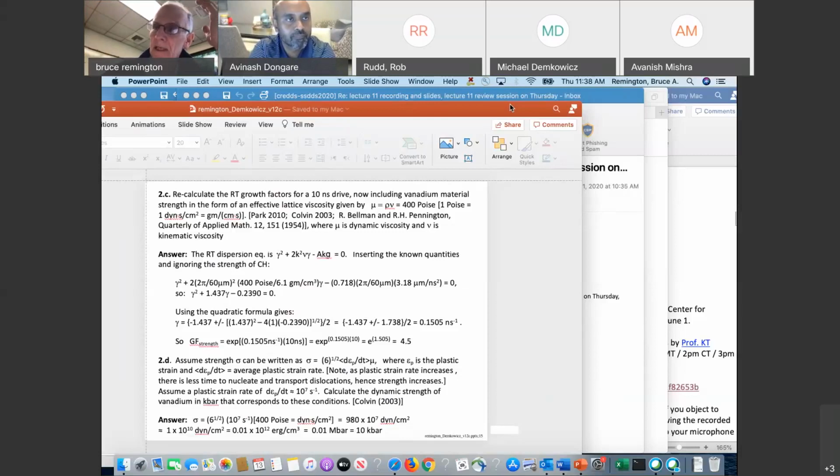One team, the strength team that I'm on, has usually been trying to keep the temperature low, because in the beginning days when we were trying to develop the experiments, there was always the worry that we unintentionally melt the sample. So we got used to running experiments where the predicted and measured temperatures were factors of 5 to 10 below melt. But more recently, we're saying we also want to turn the temperature up, but still keep it solid, to make sure we understand the temperature dependence and get closer to the melt curve. And so we're slowly inching our way in that direction.